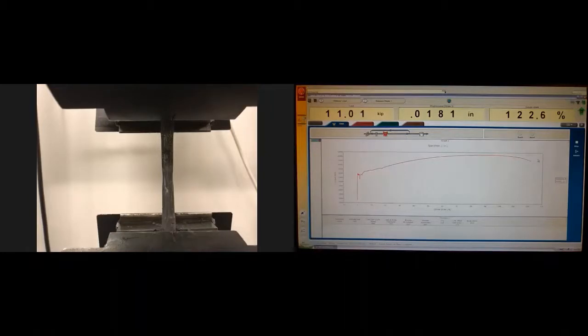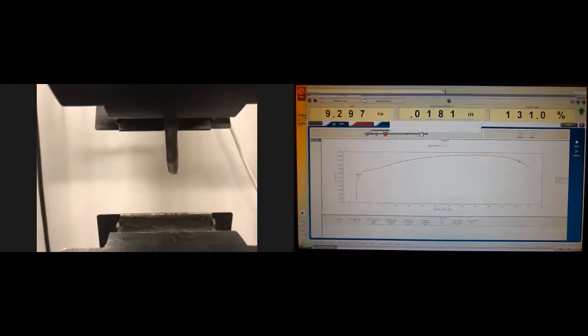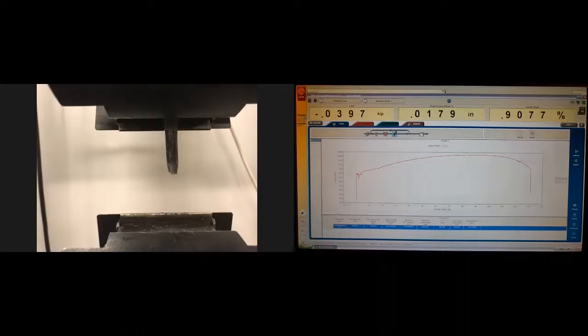And this reduction in cross-sectional area is, you see, associated with no further increase of force. So it means that we really are incapable of increasing or improving strength anymore. We are actually leading the material towards fracture right now. And this was the breaking point. And now, as you can see, after breakage, the sample fractured, the sample failed at that point, and we see that there is a huge drop in force and the machine stopped.